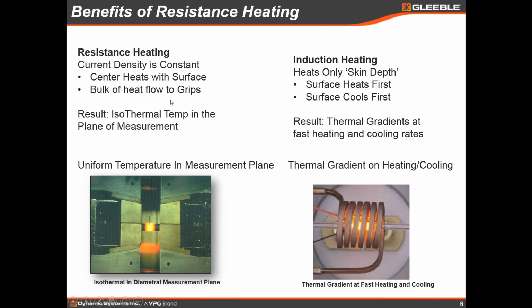The same actually holds true on cooling. Again, in resistance heating, looking at the picture on the left here, we have a Gleeble sample that is primarily cooled by these copper grips, and these copper grips are in these water-cooled jaws. So what you get in the Gleeble setup is almost all the heat, not all of it, but almost all the heat in the Gleeble sample is actually being extracted through the ends of the sample to the water-cooled grips. That means that I keep, even on cooling, this isothermal plane. Remember, we're measuring in the diametral direction here. This isothermal plane maintains approximately the same temperature at the surface as it does in the center, because the primary heat loss is not to the surface and radiation out to the environment, but through these water-cooled jaws, again keeping an isothermal plane in the center. This means that I can cool at a very, very fast rate. I can maintain that isothermal plane in the center.